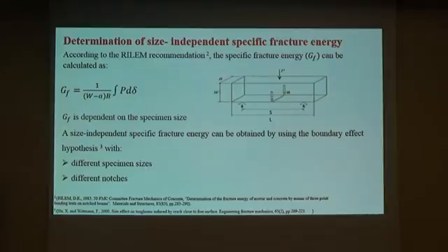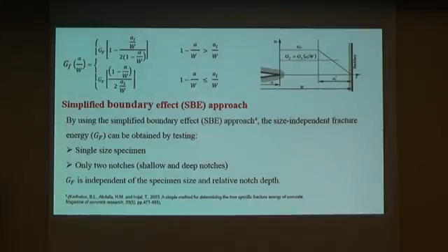After that, Hu and Wittmann proposed a methodology called the boundary effect hypothesis to obtain size-independent fracture energy, depending on different sizes of specimens and different notches. After that, Karihaloo et al. simplified this method to obtain size-independent fracture energy by testing just a single specimen size and only two notches, shallow and deep notches.